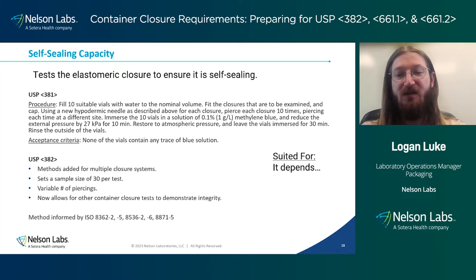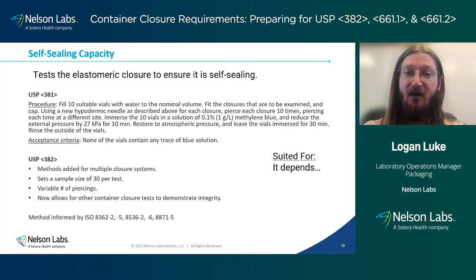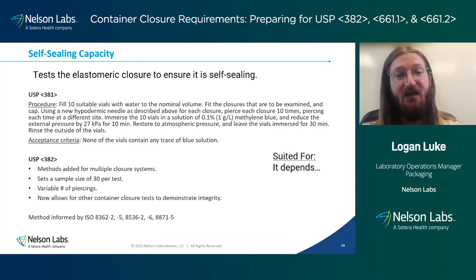What I found interesting is that the number of recommended piercings, for the methods that do have recommendations, was also considerably less than the 10 that was in the original method. And instead of needing to do that methylene blue dye test now, you can use any container closure test that you justify as suitable for testing container closure integrity.